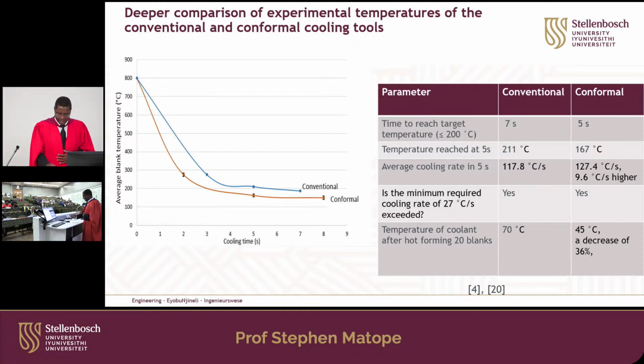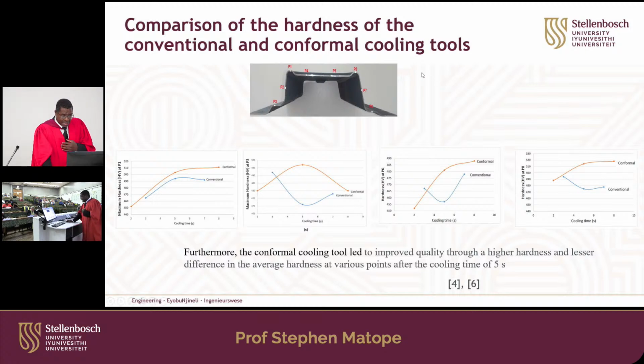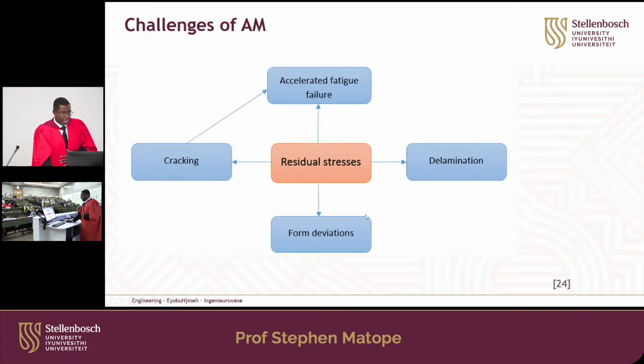and also life. Now, when we look at the other requirement to do with hardness, for that orange, you see that the hardness there was quite high in all cases as compared to the conventional, the straight cooled, if we're looking at a cooling time of 5 seconds. So we say we really managed to do better there.